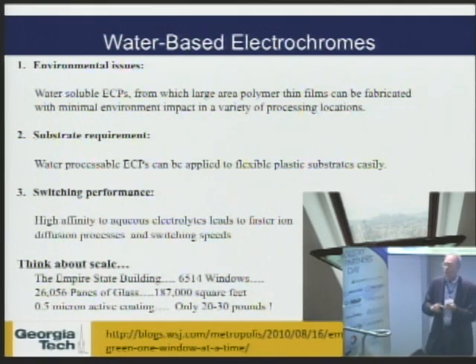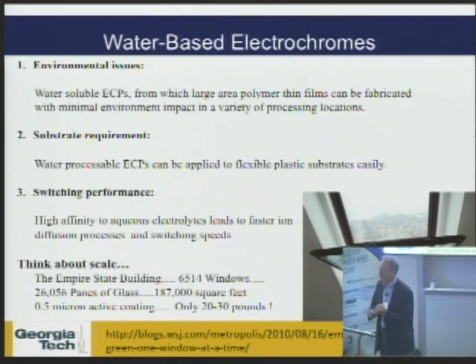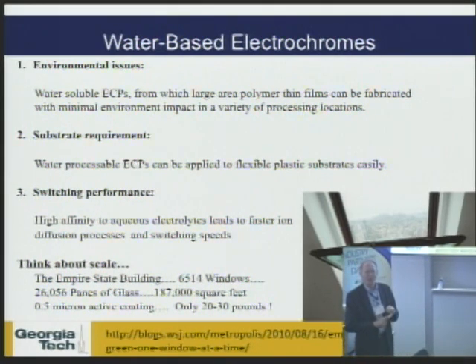Now, those are not electrochromic windows, unfortunately. Those definitely are not my polymer, unfortunately. But if we were to put a 0.5 micron active coating of our ECP material onto the Empire State Building, it would take 20 to 30 pounds of the polymer, in essence, to coat all 187,000 square feet.